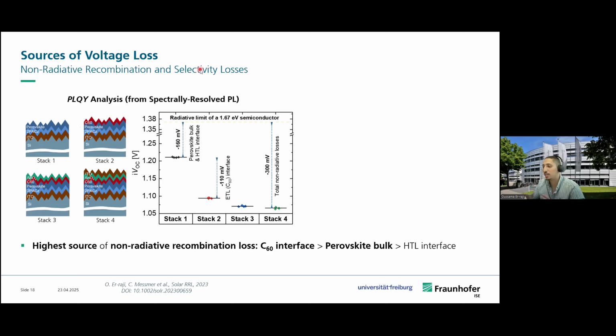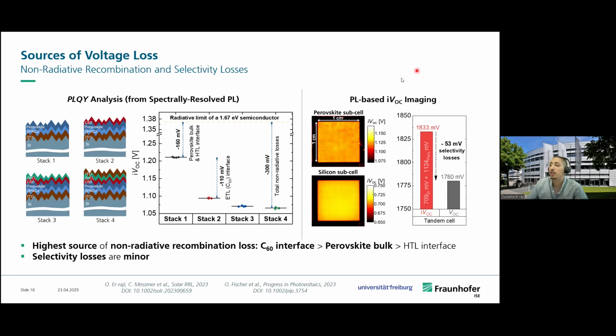Now let's compare this to the selectivity losses. Selectivity losses are based on the fact that we have a certain IVOC in our device, and then the VOC of the device is lower. So the IVOC minus VOC, or let's say the quasi-Fermi level splitting in the whole tandem cell minus the VOC of the cell, gives us an estimation of the selectivity losses. How do we get this? We can measure PL-based IVOC imaging.